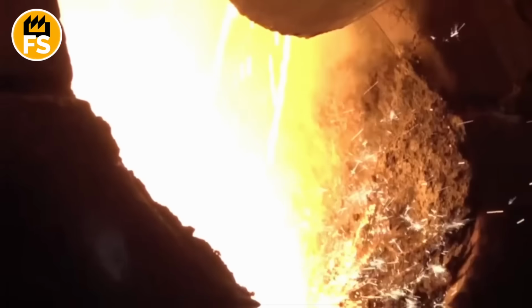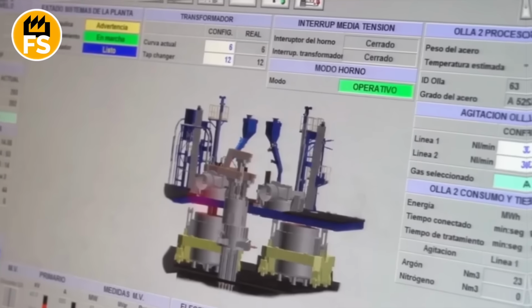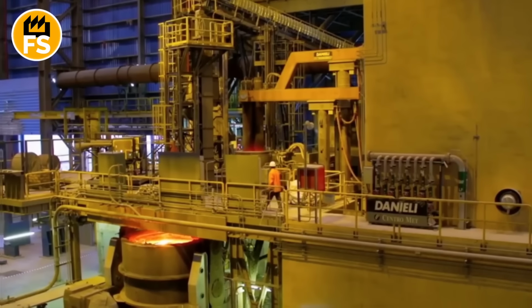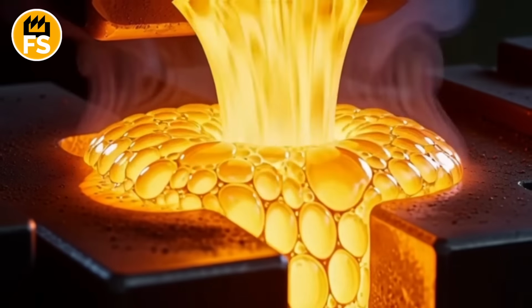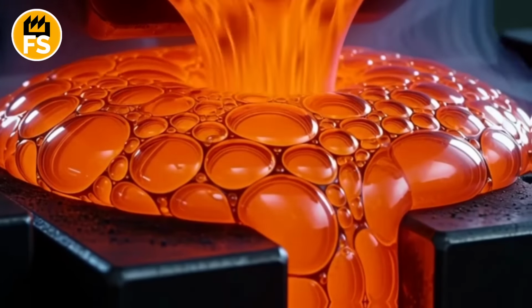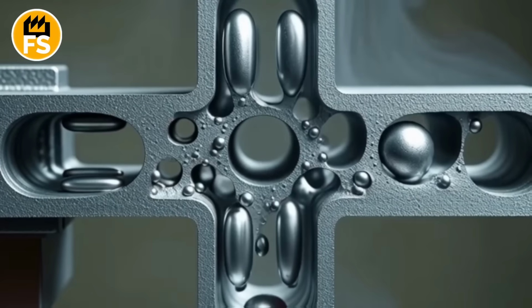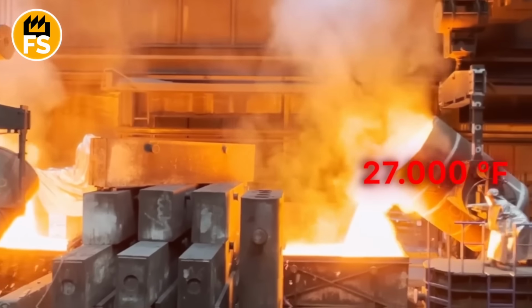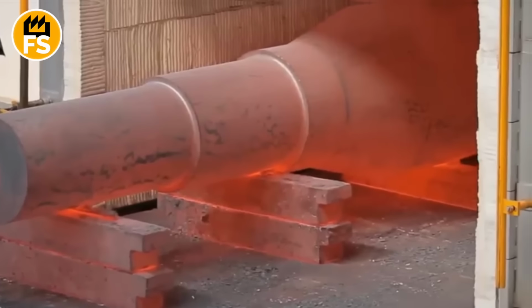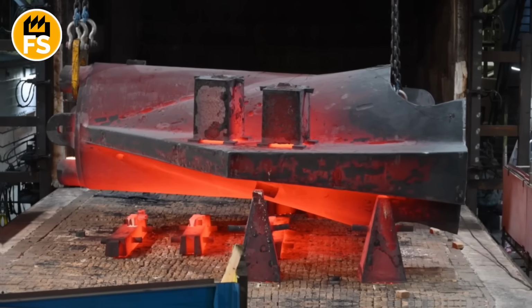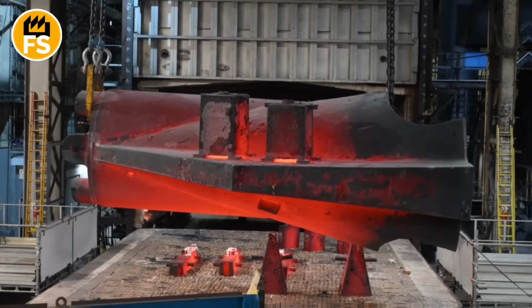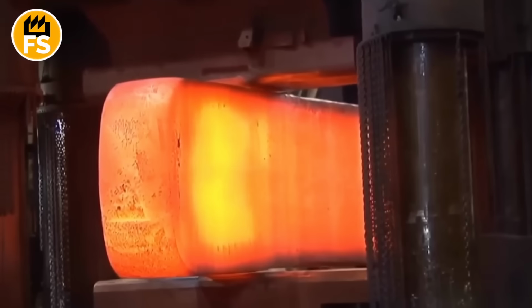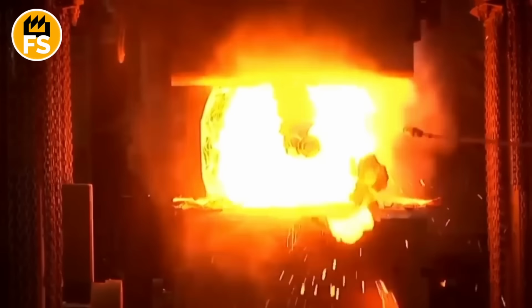During casting, the steel must be fully degassed. Oxygen and nitrogen levels are controlled at levels often not exceeding 20 parts per million. Excess gases can cause microvoids to form inside the monolith during cooling. Immediately after pouring the molten metal, which can exceed 2700 degrees Fahrenheit, time becomes the most critical factor in this process. Unlike small ingots that can cool quickly, a steel giant weighing hundreds of tons cannot be cooled rapidly. If cooling happens too fast, it leads to massive internal stresses, cracks, and structural defects because the outer layer solidifies while the steel inside is still liquid.